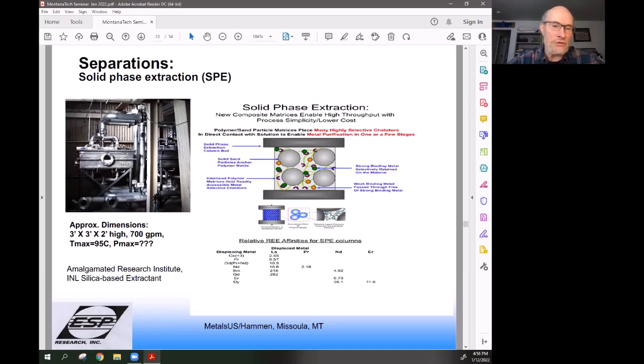A couple of folks have developed some other ways of doing this by sticking different ion exchanger-like systems directly onto the silica surface. And if you stick it on a silicate surface directly and covalently bond it there, you are then able to have much higher temperature stability in those systems and pressure stability. Shown here is an example of a beet juice softener, which took a tank, well, I'll show you in a moment. We took the tank from 8x10 down to 3x3. So it's pretty exciting. Next, please.